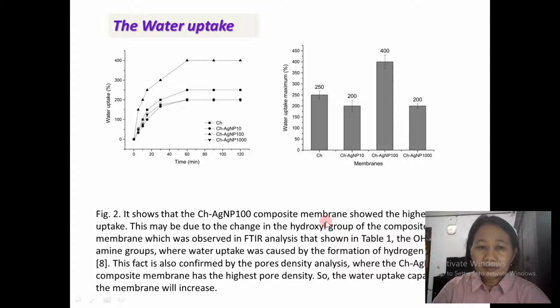For the water uptake, in this graph we saw the rate at which the membrane absorbs water. We can see that in the first 20 to 30 minutes, the membrane absorbs water very fast, and then after that it increases gently, and then finally comes to the saturation condition. It means the membranes cannot absorb water anymore.